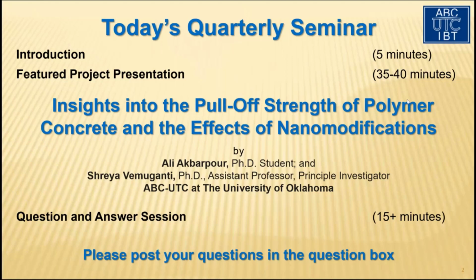So for polymer, the particular test we were talking about, ASTM C1583, is conducted after the polymer overlay has cured on the substrate. It's not specifically under a load, but after the deck has experienced some load, if you want to repeat the polymer pull-off test, and the results vary, then that is something to consult the engineer about as well, to look into whether the loading cycles or the intensity of loading has any kind of impact on the bond